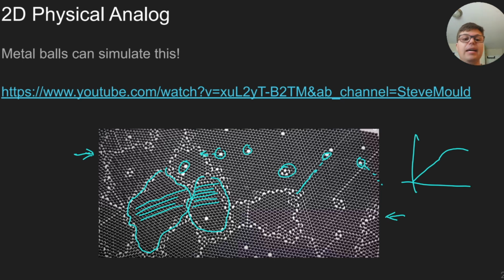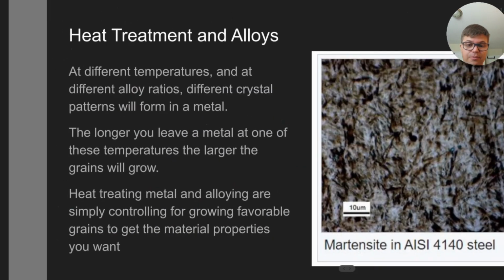So when the material actually falls apart and snaps, that's so many dislocations moving that they start piling up at these crystal boundaries, and a pile-up of a bunch of these dislocations at a crystal boundary can start to form a crack. And then that crack can propagate, and the crack can get bigger and bigger by snapping one atom at a time through that crack until the material actually snaps apart.